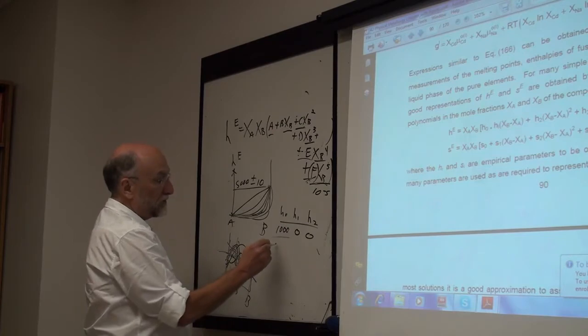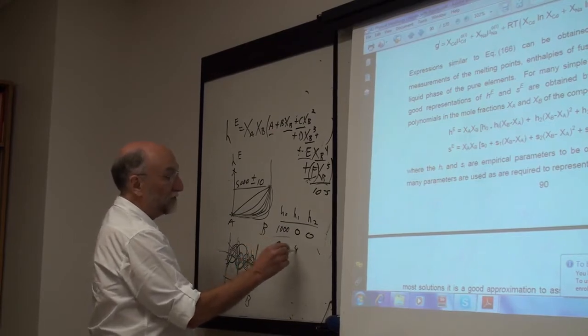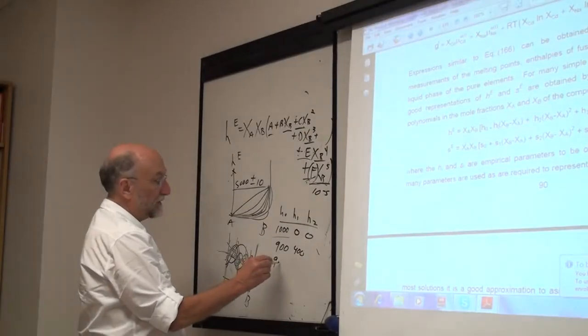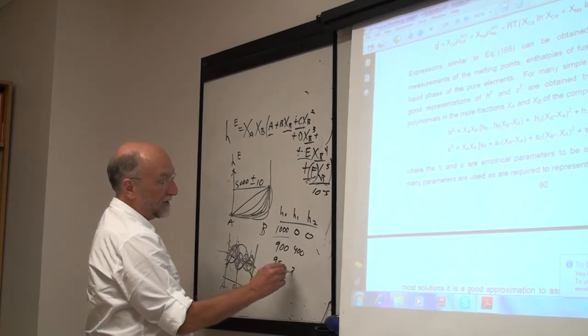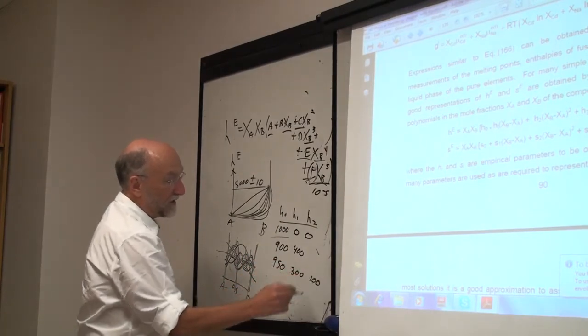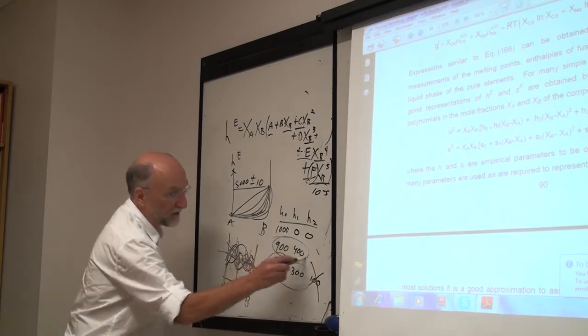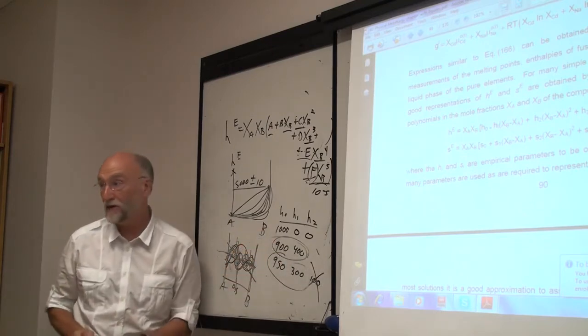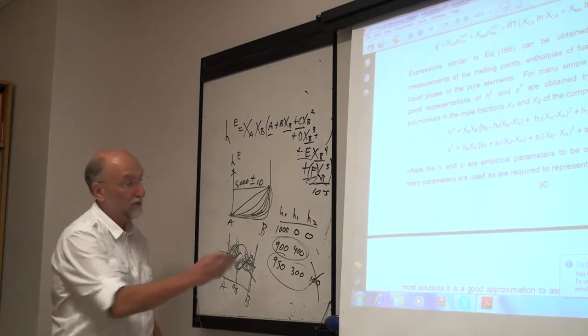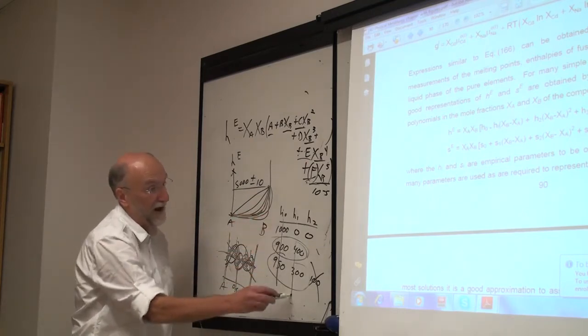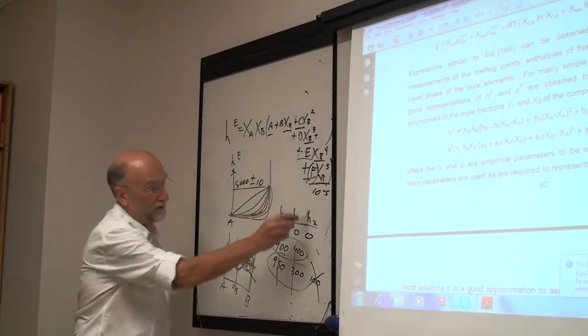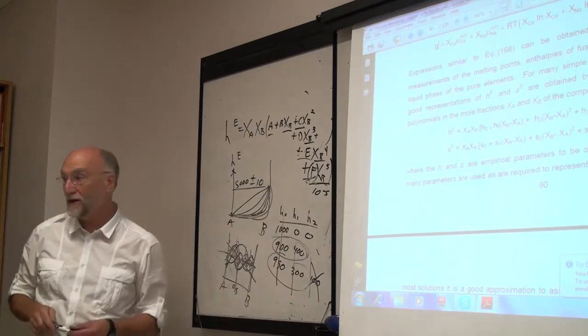You use 2 terms, you're going to get something like 900, 400. You use 3 terms, you might get 950, 300, 100. So you decide you don't need the 3rd term. You can't just drop it, but at least you see they're not changing very much. So this really is the average value. This is your average first derivative, this is your average quadratic character, and so on.